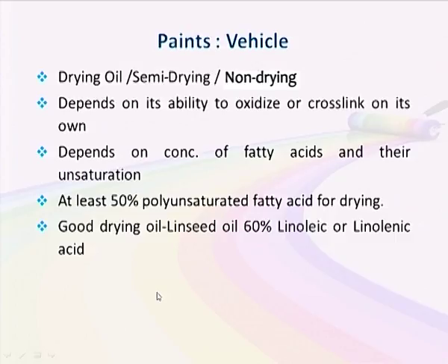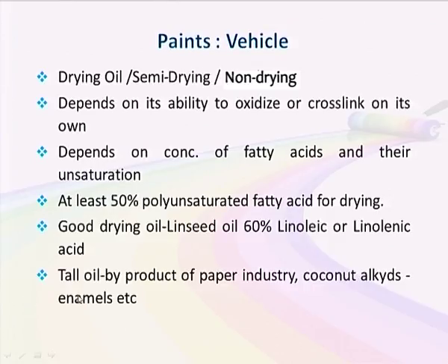An example of a good drying oil is linseed oil, which consists of 60% linoleic acid or linolenic acid. Tall oil is also used as a vehicle. This is a byproduct of the paper industry. Coconut alkyds are also used as a vehicle for enamels, etc.